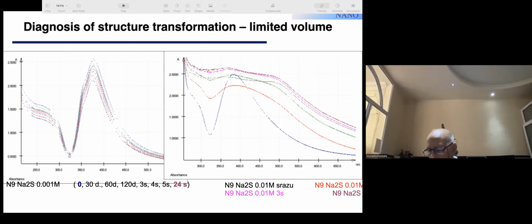if the quantity of sulfur ions is limited, you can form thin films on the surface area of nanowires, and by controlling the concentration of sulfur ions in solution, you can control the thickness of the forming